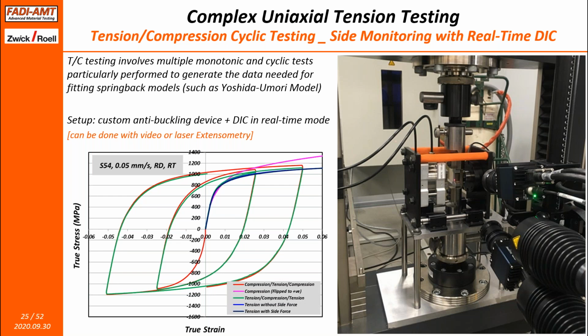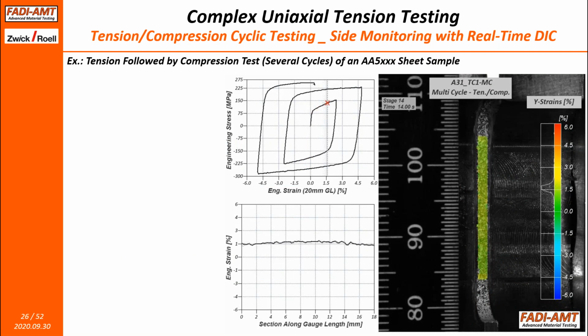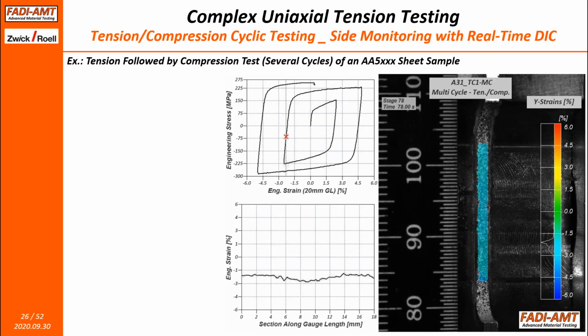Not only just measure them, we need to measure them in situ of the test so that we can design and execute those tension and compression cycles that you see on the left-hand side. We should be able to monitor the strains during the test and then reverse the machine when we hit a particular value. And that's basically what can be done with the DIC. And again, it's difficult, if not semi-impossible, to do with conventional extensometry.